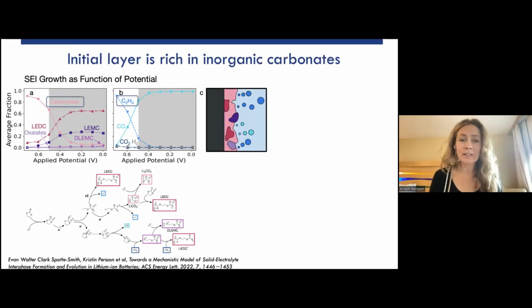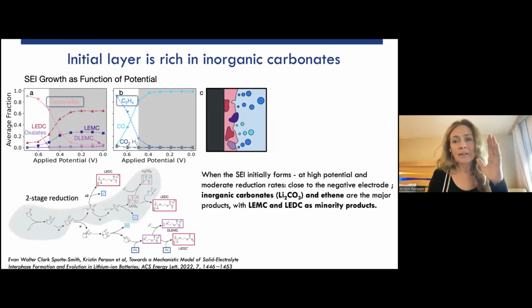In this particular case, with the species I just mentioned, as we form the first SEI, I assume I have a completely bare anode, so there's virtually no tunneling barrier. We're using Marcus theory to get an idea of how much resistance there is for the electrons to tunnel. It's all by first principles. There are no fitted parameters. We come down in potential to around 0.7 volts. EC starts reducing, with ring opening.